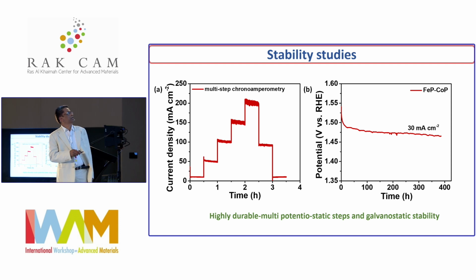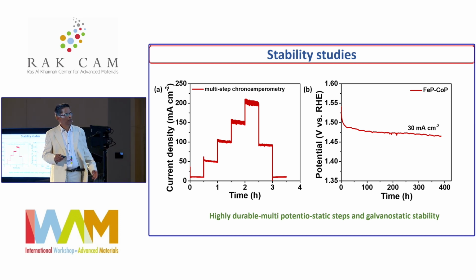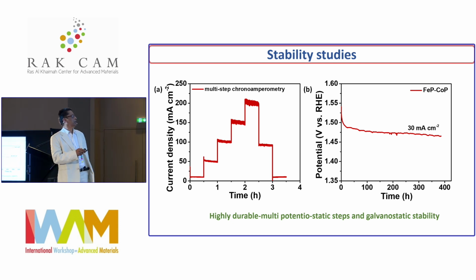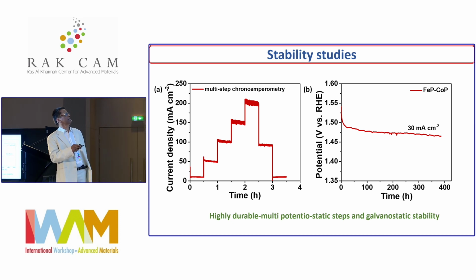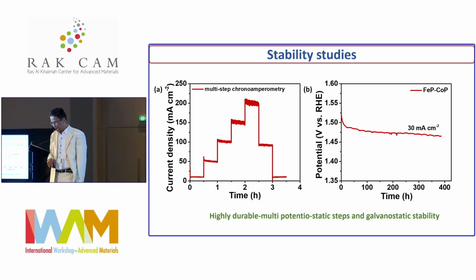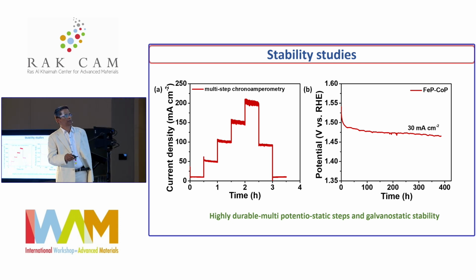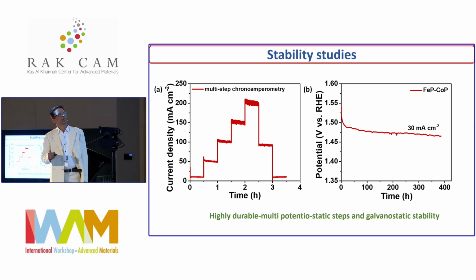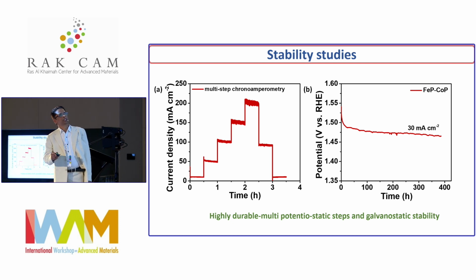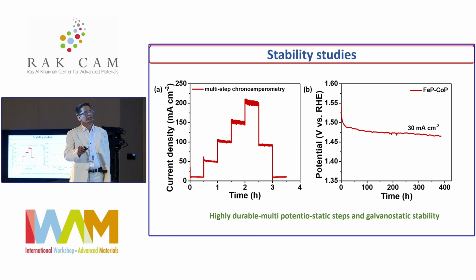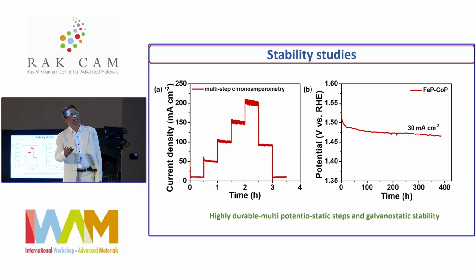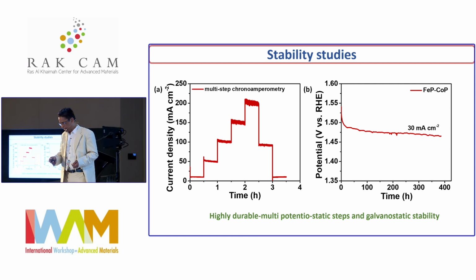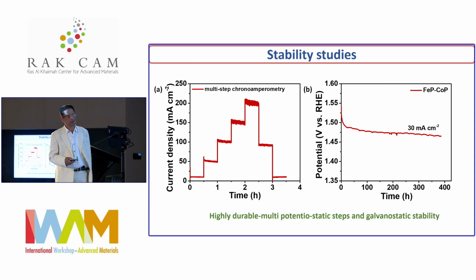And even stepwise multi-step chronoamperometry shows that it's versatile to look at any current density. You can see that it is very stable over a period of a few hours, and you can also bring it to a step-down approach. Looking at this one, you can see that at 30 milliampere per centimeter square current density, you can even keep this potential almost constant. In fact, over 300 hours, the potential is even coming down. So that means there are still structural transformations happening during this process itself.